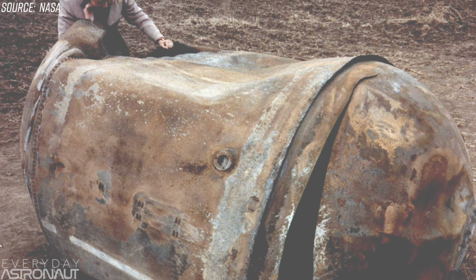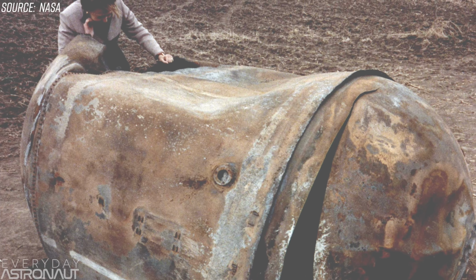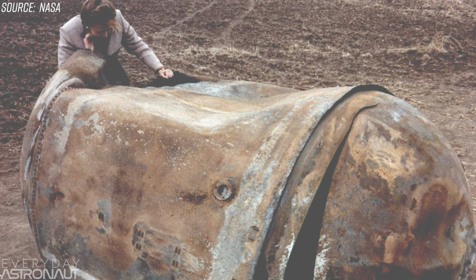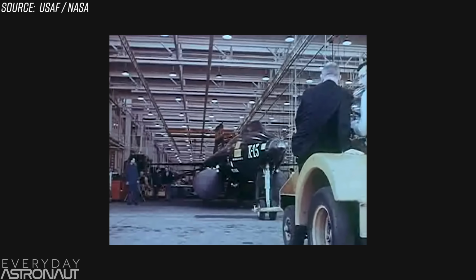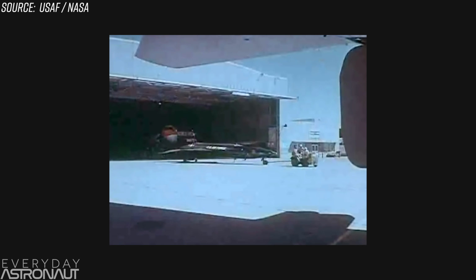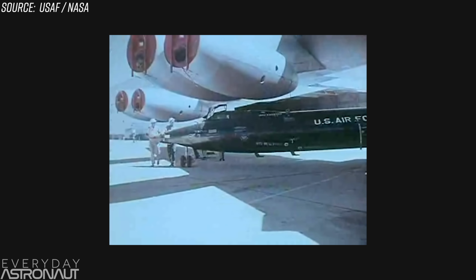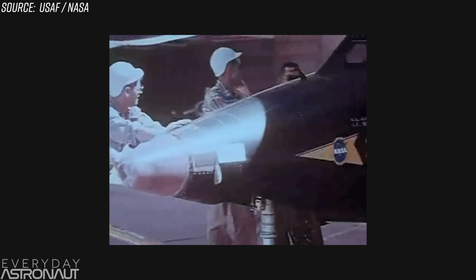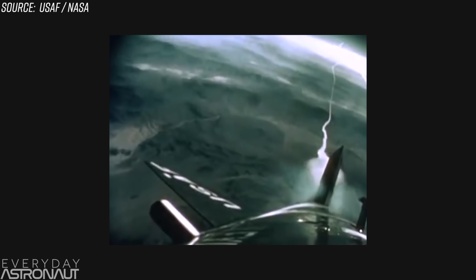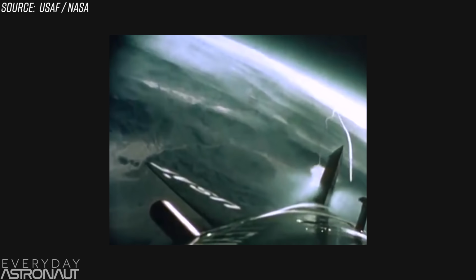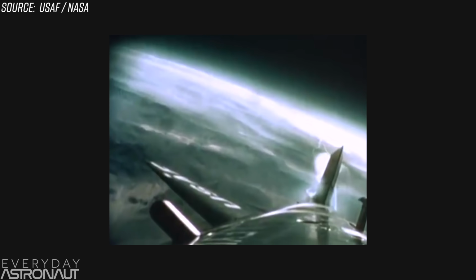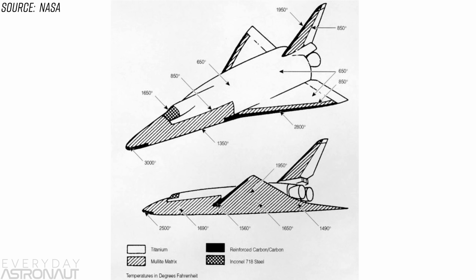This is a stainless steel tank off a Delta rocket that survived re-entry basically intact. Or there's the X-15 hypersonic rocket plane, which was actually made partly of Inconel, which has an extremely high melting point. This is called having a hot structure, and that's where you basically let the structure of the vehicle get really, really hot. And there were even considerations to build the shuttle out of titanium, which would have meant it wouldn't need nearly as much heat shielding.